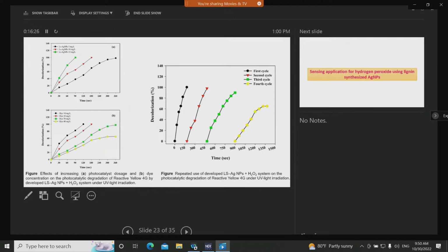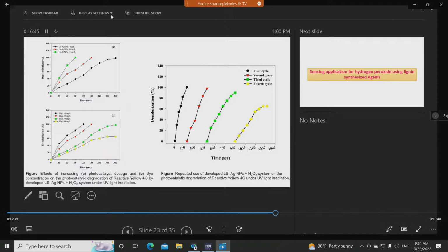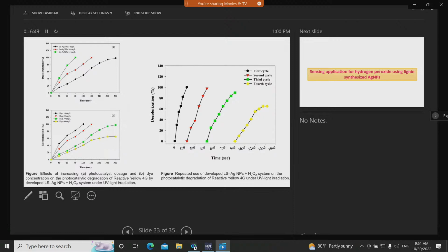For achieving better performance, optimization of photocatalyst dosage and dye concentration on the photocatalytic degradation of dye is very important. So here we have performed the optimization condition in which, in both the photocatalyst dosage and the dye concentration, the photodegradation was achieved in less time, about 360 seconds, which is lower than other reported studies.